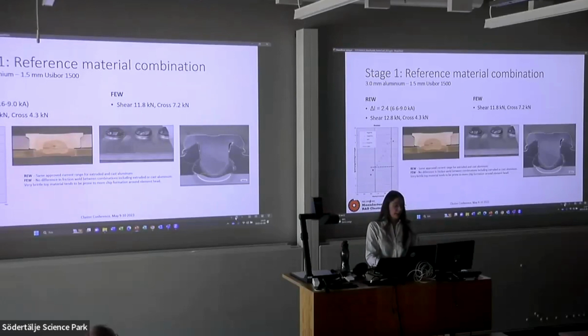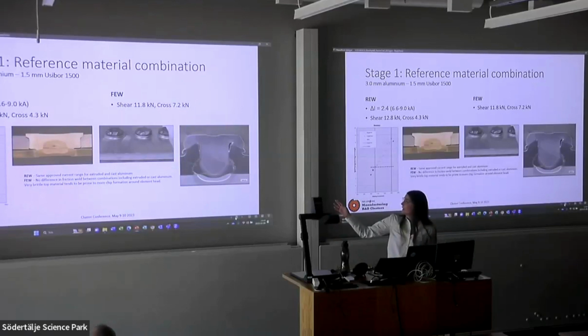Just when comparing joining cast aluminium or extruded aluminium, we saw for resistance element welding the same approved current range. With friction element welding, we saw that when we used cast aluminium alloy without heat treatment, it was very brittle, and therefore you tended to get more chip formation around the head of the element. And the chip formation could work as an initial point for galvanic corrosion, for example. But here in the image, you actually see the other cast aluminium alloy, where we don't see the same problems because of the increased ductility.